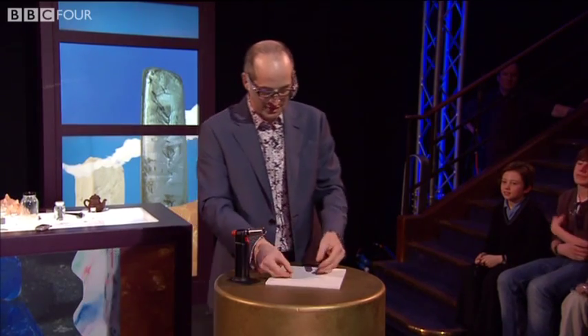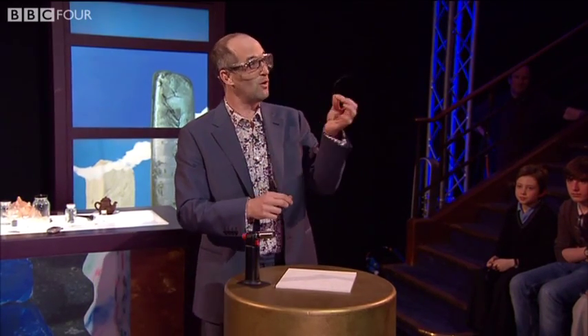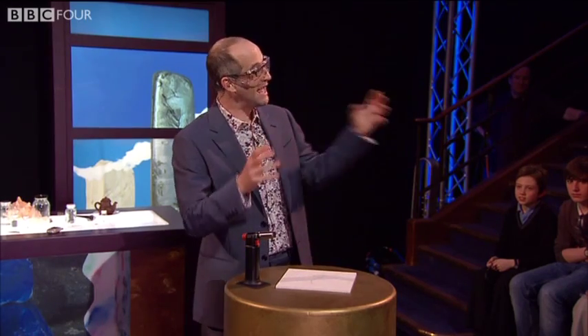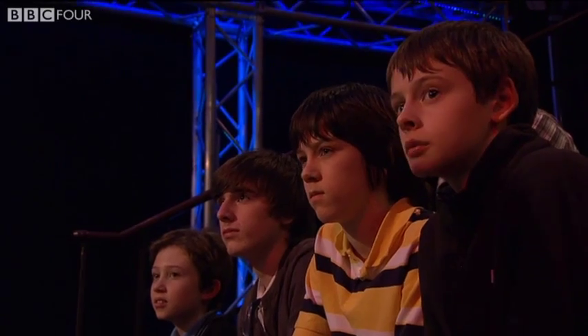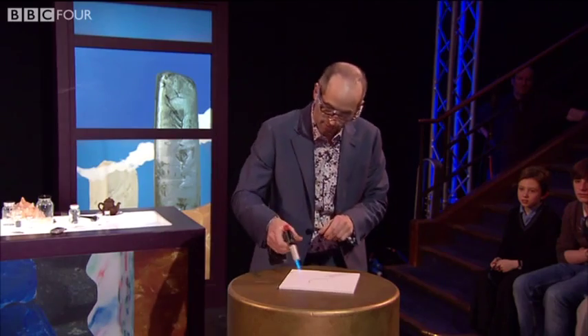But they have been trained. They've been trained to know who their neighbors should be, so that they have a particular shape if they all get next to the right neighbors in the right orientation. But when I pulled it apart, I separated the right neighbors, so now it's not in the right shape. And I can jog the memory — I can let the neighbors get back to each other and recover the shape of the paperclip just by giving them a bit of heat. That's a bit of energy. They jostle around, they find the neighbor they want, and off they go. So watch this.